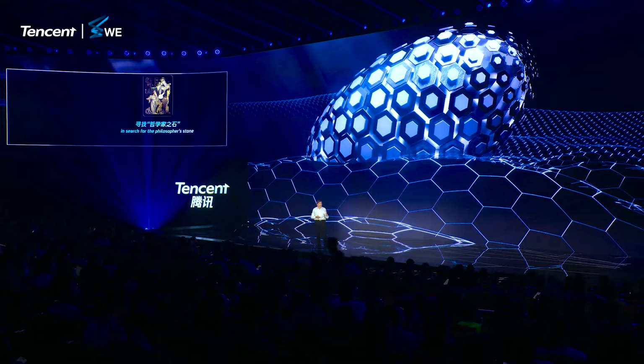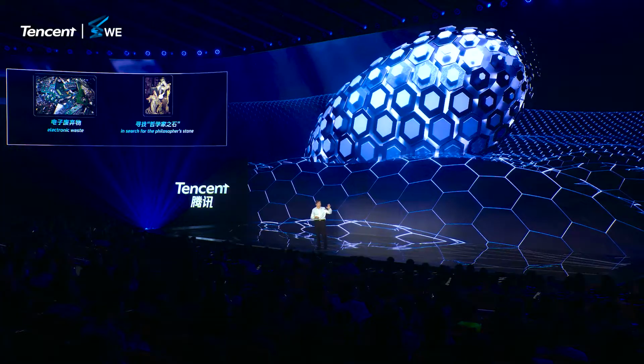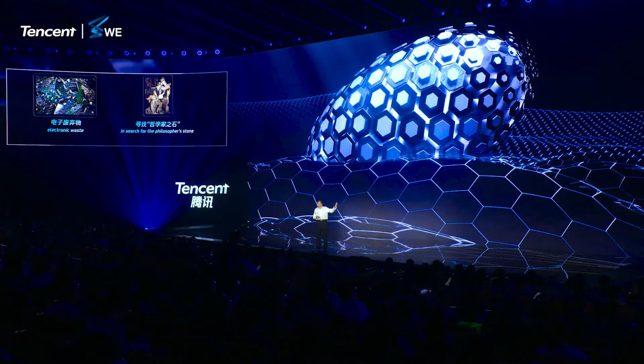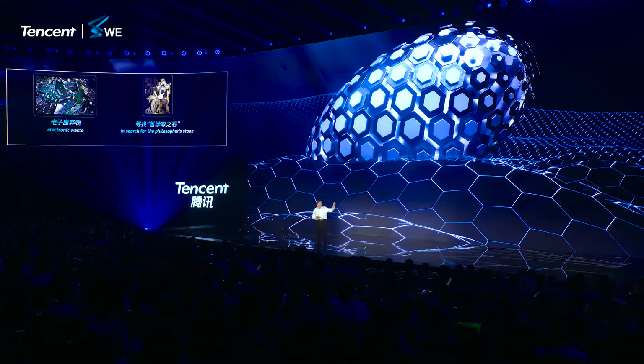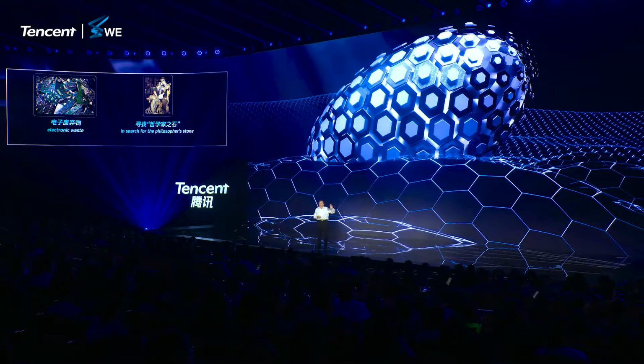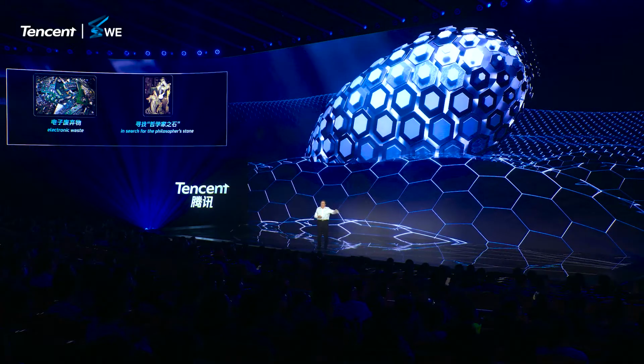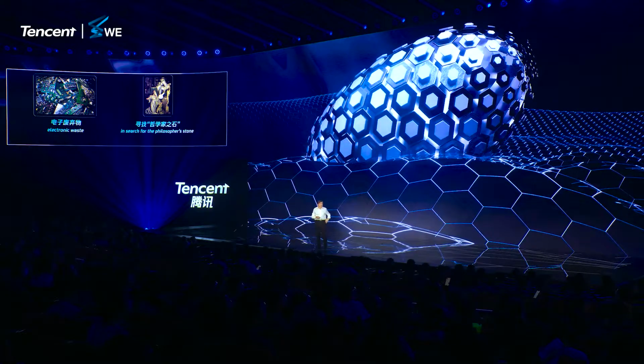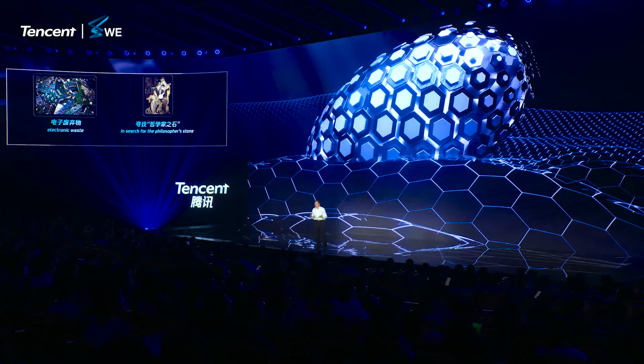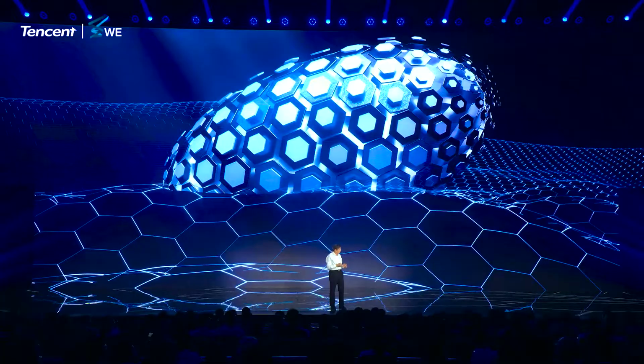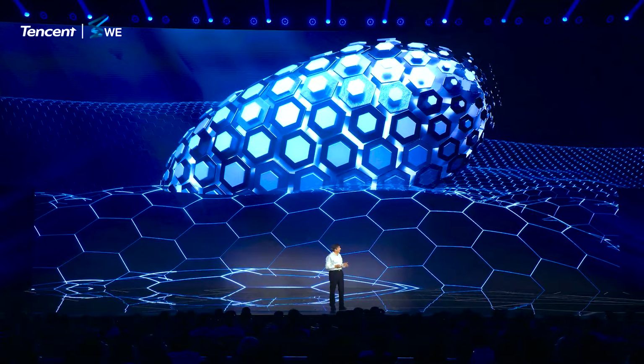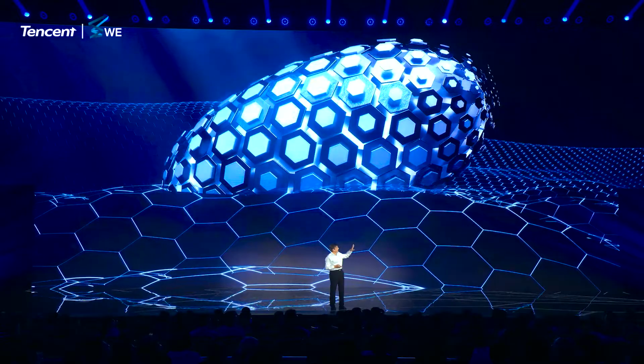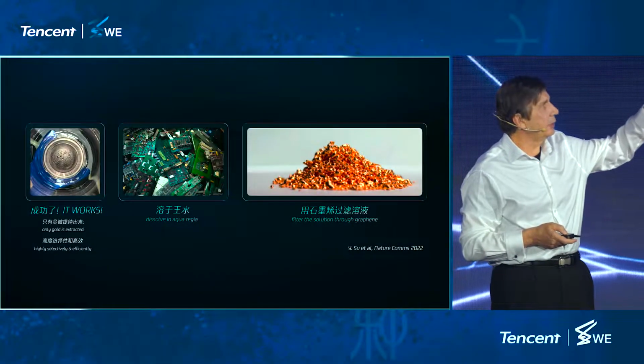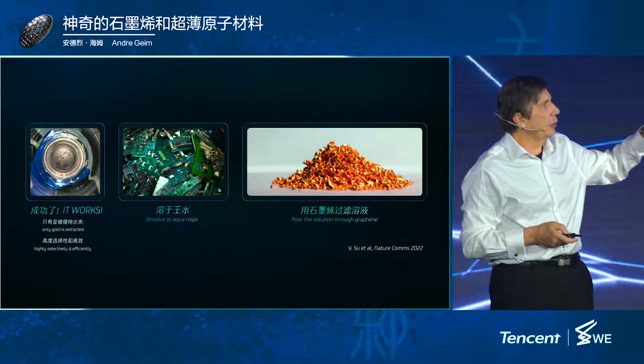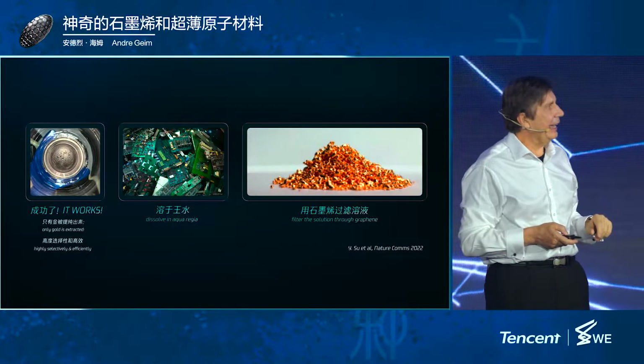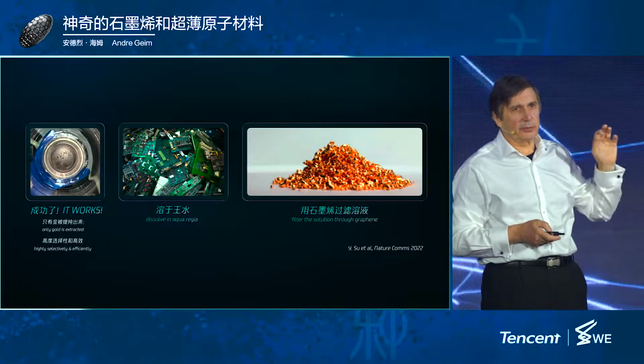But in our case, we use electronic waste. There is a lot of this electronic waste around, and there are a lot of important materials inside, gold, silver, cobalt, nickel, and so on, and you would like to extract and recycle this equipment. It's hard to do, but with graphene, it turns out to be possible. What we did here, we literally dissolved what you see in the picture in a strong acid, and then poured this acid through a collection of graphene flakes.